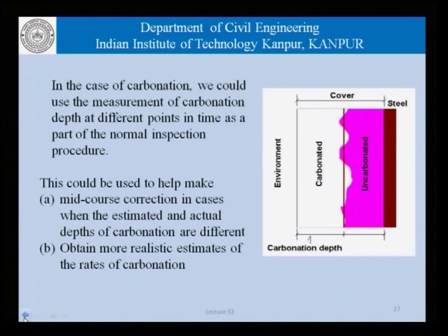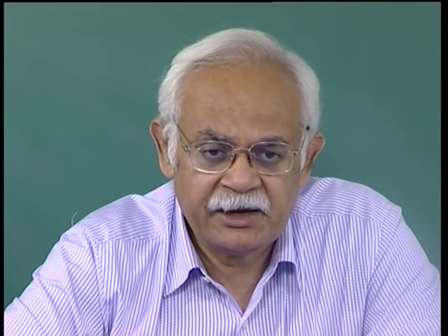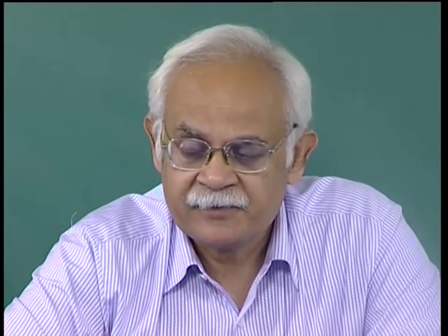So, what we are saying is that if we measure the rate of carbonation at some point here at time t equal to T1 and find that this is the depth of carbonation that we actually find, this should be compared with the x1 estimated, that is, at this point T1 what was the estimated value of x1. If we compare this x1 estimate versus x1 actual, then we will know whether we made a conservative or a non-conservative estimate in terms of the propagation of carbonation.